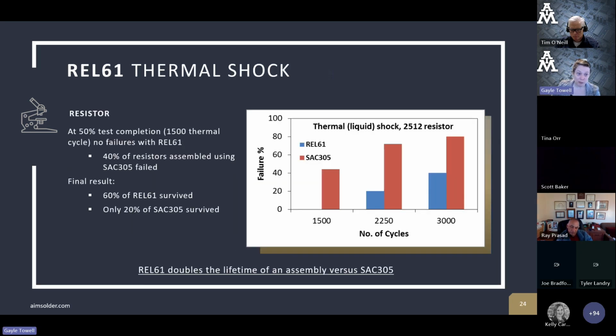This is thermal shock performance. REL61's thermal shock performance approximately doubled the lifetime of an assembly versus SAC305. Thermal shock is like thermal cycling, but you make the temperature change a lot faster. Here we see after 1,500 cycles, there are essentially no REL61 failures, but we've got quite a few SAC305 failures. Then we start seeing some REL61 failures when we get to 2,250 to 3,000 cycles and so on, but it's still massively outperforming SAC305.